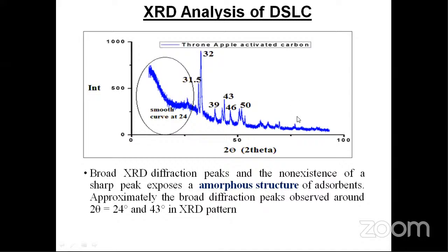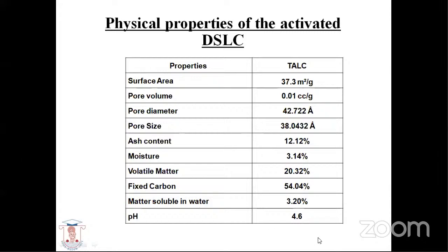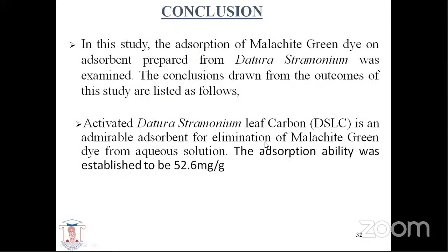So it shows the amorphous structure of the adsorbent. I also analyzed many physical properties like surface area, pore volume, pore size, ash content and moisture of the DSLC. In conclusion, in this study, the adsorption of malachite green dye on the adsorbent prepared from DSLC, that is Datura Stramonium leaf carbon, shows 52.6 milligram per gram of the adsorbent.